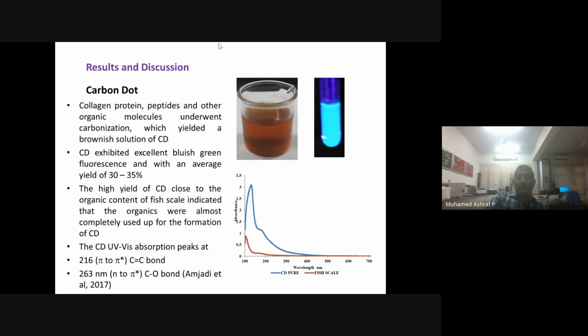Then I will talk about the carbon dot we have synthesized from collagen. Collagen protein and peptides were converted to this carbon dot. Generally, you will get two peaks in a carbon dot. One is the major peak, which comes around 220 to 230. What does it mean? It is a C=C double bond. This carbon dot is a conjugated carbon C=C bond system, and this will show a peak due to the pi to pi star transition, and then around 263 the n to pi star, the carbon C=O bond or C-N bond, etc., will show at the second peak.